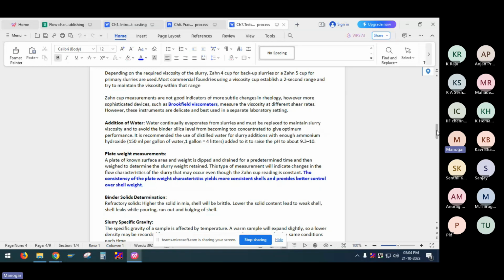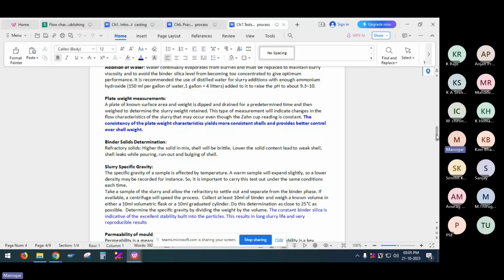And addition of water to maintain the viscosity continuously, because the water in the binder evaporates when it is stored and in operation. To maintain the viscosity and to avoid binder silica level from becoming too concentrated, to give optimal performance, it is recommended to use distilled water to keep the pH about 9.3 to 10. And the other test is